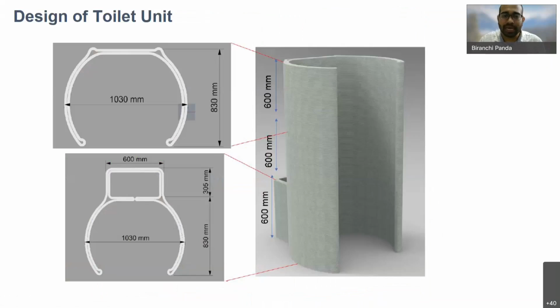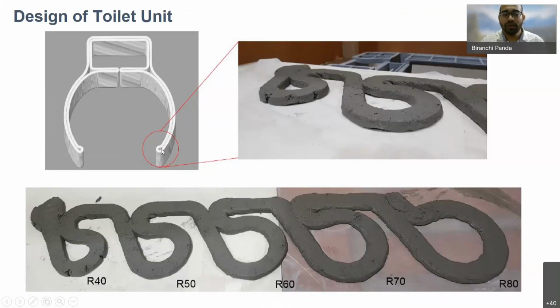So now let us talk about design. Why is design important? To do some design experiments, we printed a toilet unit. You can see this is a 1.8 meter tall toilet unit, and we have designed it. During printing, what we observed is that sometimes we have this kind of cornering issue. We call it a cornering issue because here we have a sharp radius of curvature. We found that during printing of this radius of curvature, we get some layer tearing on the outer periphery of these layers. You can see these tearings happen, and we investigated that it happens for many reasons.